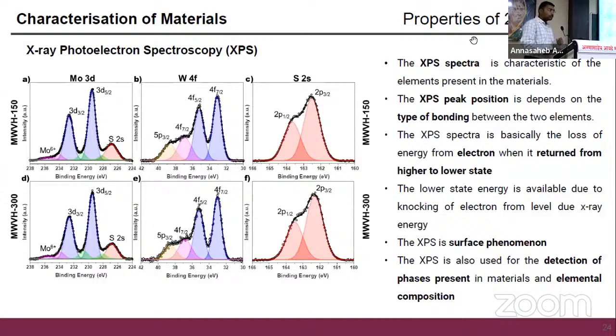You also know about X-ray photoelectron spectroscopy, which we can use to confirm the formation of sulfide, oxide, or other materials. Typically, every element has its characteristic spectra. Here, molybdenum 3D gives some characteristic spectra, and in case of tungsten, the 4F gives the characteristic spectra.